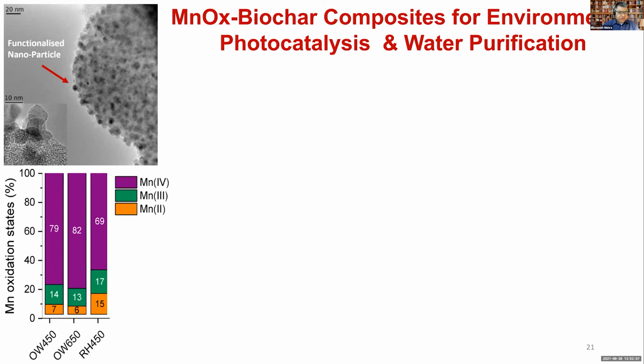In this case, oak wood at two different temperatures, 450 and 650, and also rice husk. And we tried to understand, using linear combination fitting, what the ratio of different kinds of manganese is in the bulk of this system. And of course it is mostly manganese 4, but that's not enough for us to understand this material, so we have also tried to understand the carbon chemistry using XPS and tune the porosity and so on.